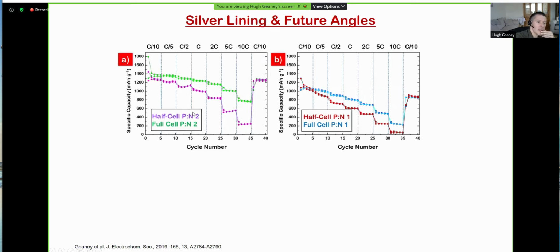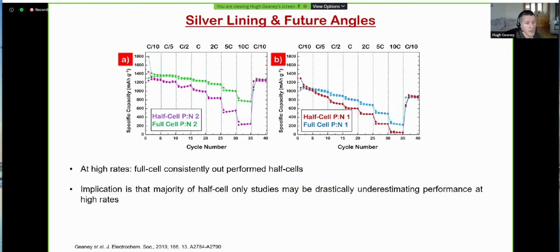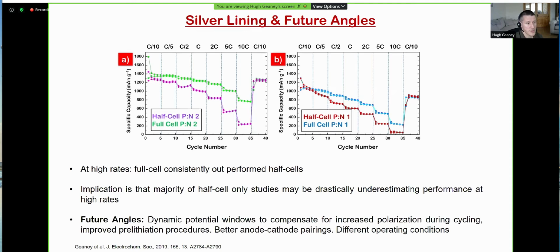You can see that in each case here, the full cell performance is actually drastically higher than the half cell performance, particularly as we go to 10C here. In this case, the full cell is actually giving us a capacity that's nearly twice, or more like 3 times higher than the equivalent half cell. So at high rates, the full cell consistently outperformed the half cell. The implication of this is that if you're only looking at half cells as an indicator of performance for high rate materials, you're drastically underestimating the performance at those high rates.